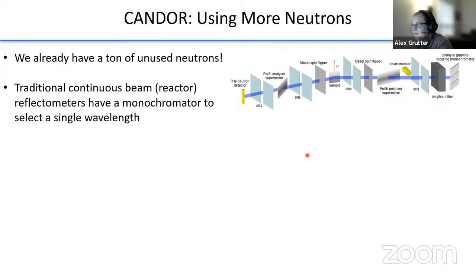Our uncertainties in neutron reflectometry are almost exclusively determined by counting statistics, i.e. how many neutrons did we actually count at a given angle? And so the answer is that we need a lot more neutrons. And the fortunate answer is we actually have a lot more neutrons than we're currently using. So a traditional design for a neutron reflectometer has a focusing monochromator at the front that then sends a specific wavelength at the sample and then bounces off into the detector.